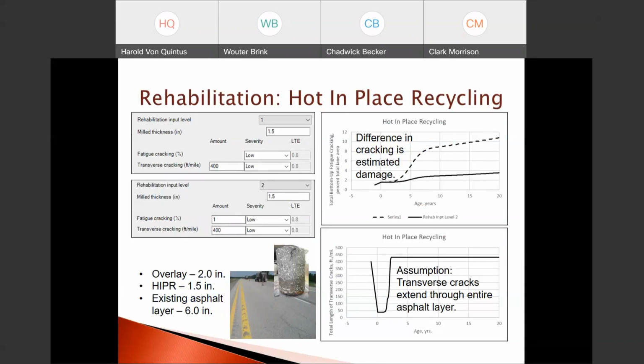So our assumption, I remember from the previous slide, originally I assumed, as shown for rehab input level 2, the lower box, we assumed only 1% fatigue cracking. And that would be that there would be no fatigue cracks on the surface. The upper rehab box at rehab input level 1 predicted the amount of fatigue cracks. So there's a big difference. And the big difference is the estimated damage.